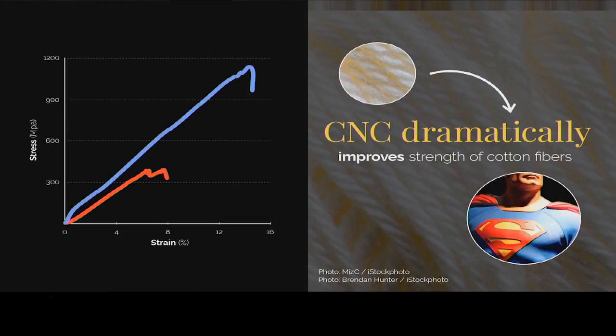Another interesting application is for increasing the strength of other fibers, like cotton yarn. We have shown that by adding only 1% to the weight, coating cotton yarn, we can dramatically increase the tensile strength of the cotton yarn. And the toughness, we've been able to increase by close to 300%. So one can make the same shirt that I'm using with 1/3 of the material, or maybe make a shirt for Superman.